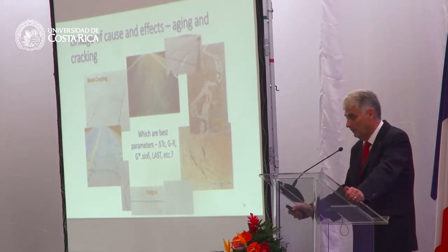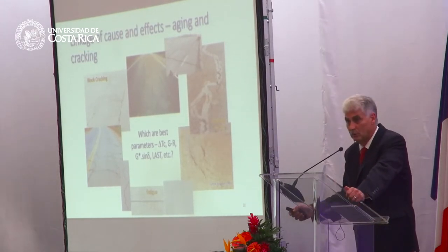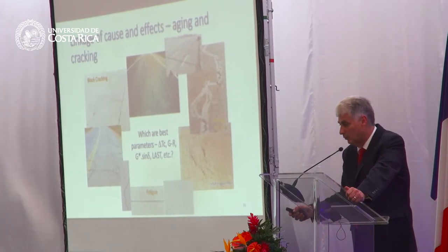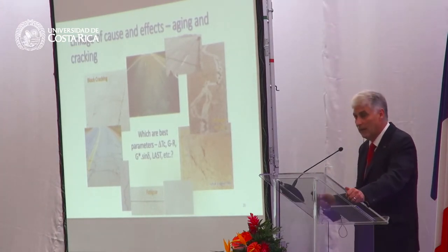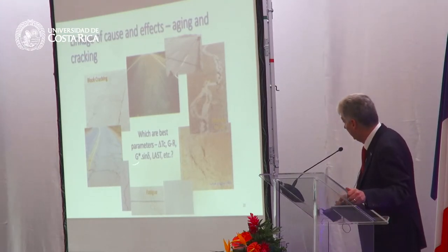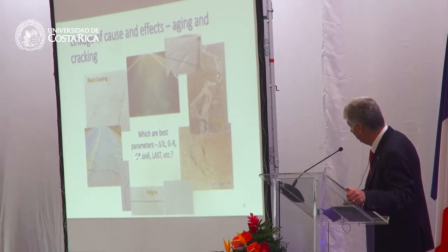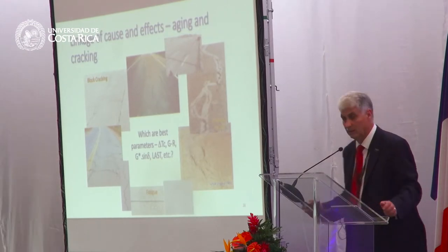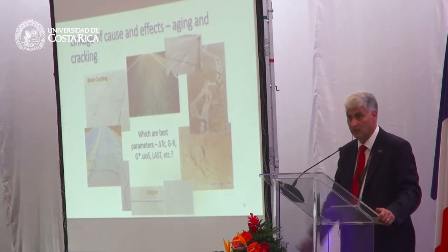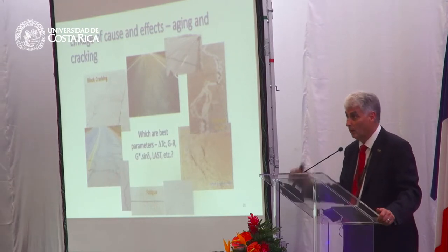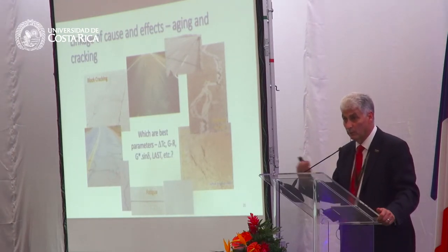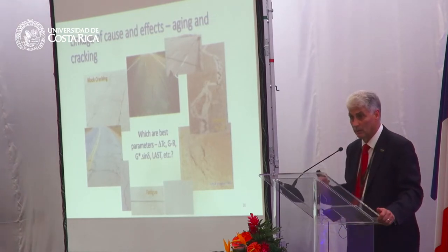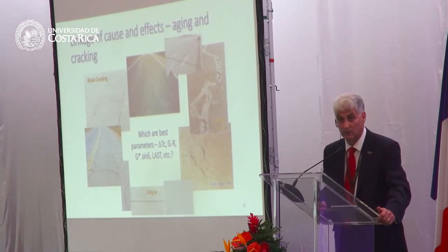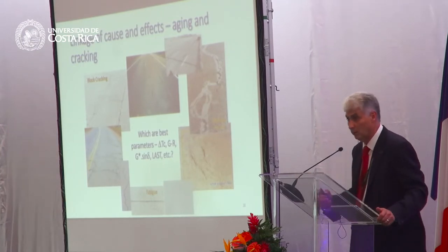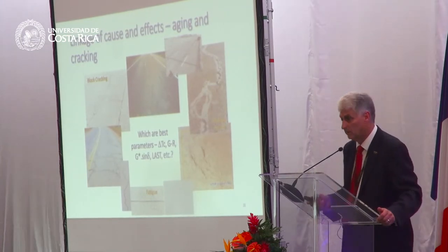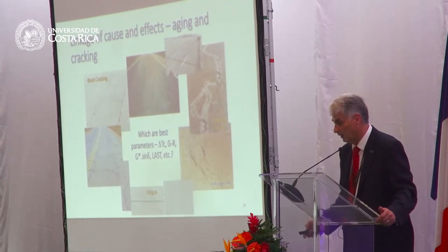I put this slide on here, and what we need to do is provide the linkage of cause and effect. Aging and cracking, we are looking at these parameters at the moment: the delta Tc, the Glover-Rowe, G-star sine delta, linear amplitude sweep tests, other tests to try to decide where we're going. I don't think we've quite got there yet, but when we're designing asphalt binders, we know that at the moment we have 2 or 3 very useful parameters that we need to consider. And certainly in the formulation work that I do around the world, these are parameters that I'm advising my clients that we need to consider.